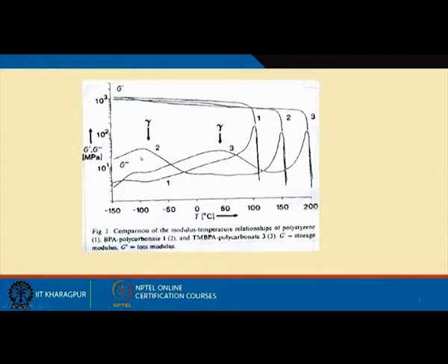So, this gamma relaxation temperature also goes up, probably because you have introduced some restriction around the phenyl carbonate bond by introducing 2 more methyl groups and thereby steric hindrance. That directly affects the rotation, and that directly affects your gamma relaxation temperature. So, now you have to go to a considerably higher temperature. Before, it was at minus 105 degrees that this rotation was possible; now only at plus 45 degrees is this rotation possible. So, this is your gamma relaxation.